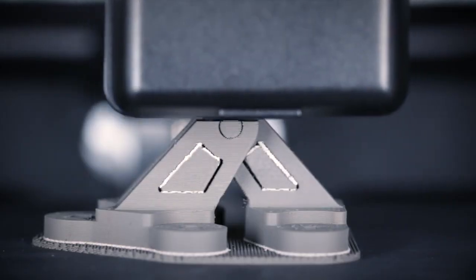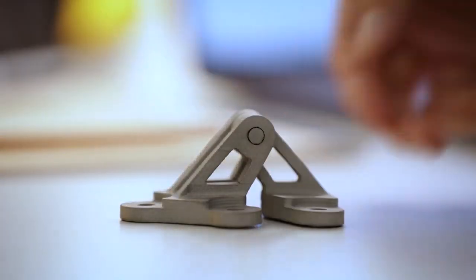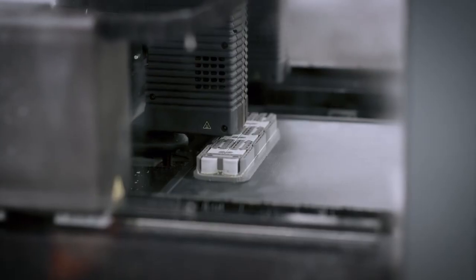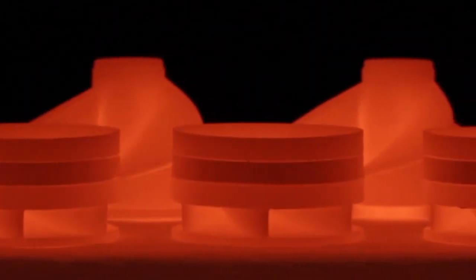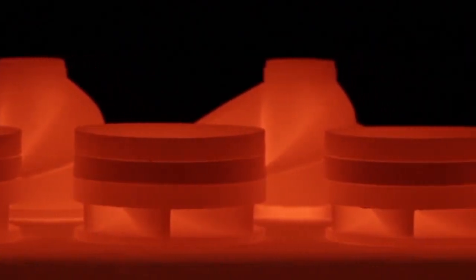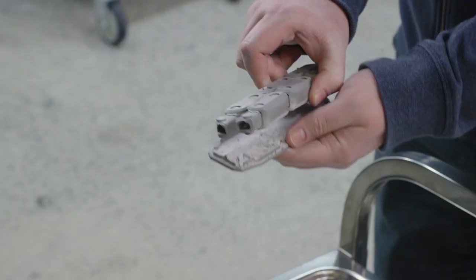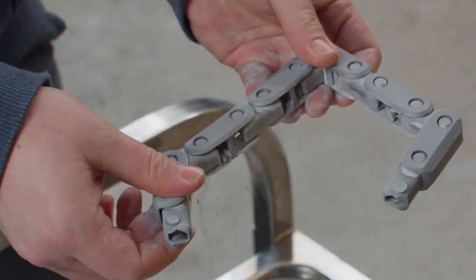technology. Our design guidelines lead users through creating functional, moving assembly parts utilizing the ceramic release material printed on the Studio System's second printhead. This ceramic release material bakes away during sintering, enabling the whole metal assembly to break away by hand and be free moving after coming out of the furnace.